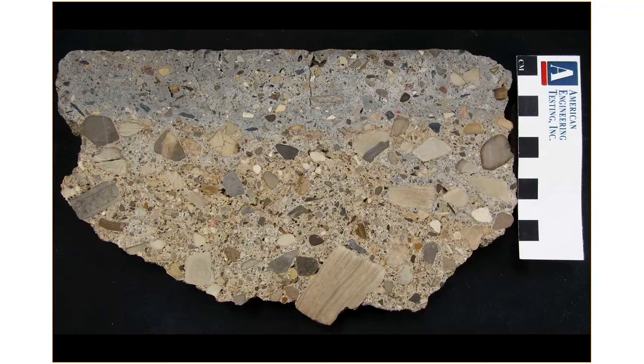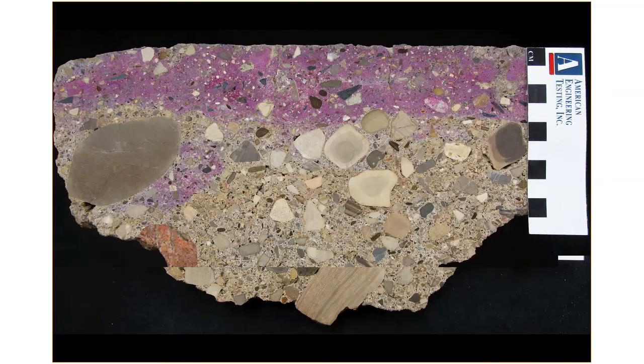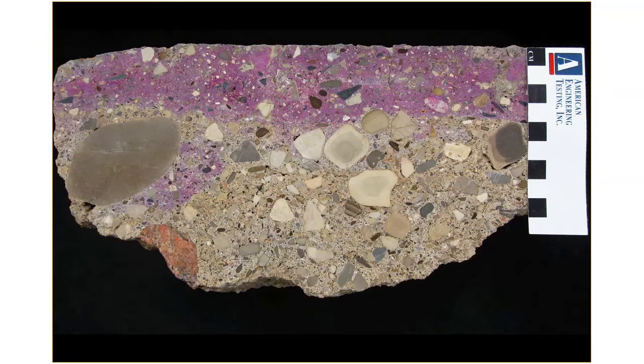And when we put a pH indicator down on this concrete, called phenolphthalein, and we stain the concrete, we're staining the areas of the concrete this magenta coloration, and that's where the high pH is retained in the concrete. So this is dense and it is not carbonated. And carbonation is a chemical change in the concrete. If anybody's been working with concrete out there, they know that concrete in a plastic state, coming right out of a ready-mix truck or a plant, has a very high pH. And if you work in it for quite a few hours, you can actually burn the skin off your legs or burn your skin on your hands because it's very caustic, and the pH is upwards of 12.5 or 13.